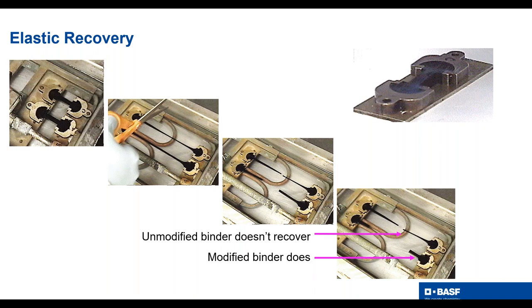And then you'll notice that the unmodified binder up on the top does not recover very much, but the modified binder does. Usually the specifications and agencies is around 55 to 60% recovery. And you'll also notice that the thickness of the elastic recovery sample on the bottom is a much thicker band, which makes it more rubber band like, and it just pulls itself back. And you'll notice that when you have a good polymer modification, you'll see that.